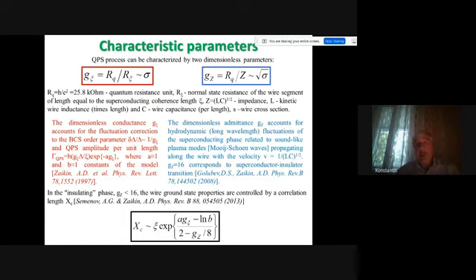It appears that in the issue of superconducting fluctuations, there are characteristic parameters. First is called G psi, which is the ratio of the superconducting quantum resistance, which is 25.8 kiloohms, to the resistance of a superconductor in the normal state of the length psi. The smaller this parameter is, the closer we are to superconducting fluctuations. For bulk samples, R psi is big, and then no quantum fluctuations are observed. And this parameter is mainly responsible for the first part of my talk I was going to speak about.